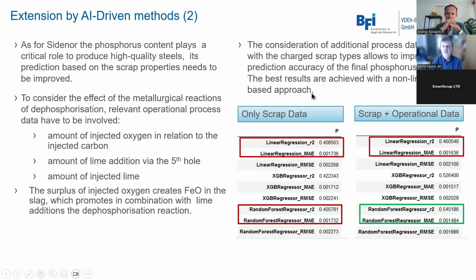So you can see here in this simple table regarding the results of different modeling approaches that when using not only the scrap data, but also in addition the parameters of the EAF treatment, like oxygen input and lime input, you can achieve a much better result regarding reliability of the prediction of the phosphorus content. And finally, we used the random forest regressor, which achieved the highest R-square value and the lowest mean average error.